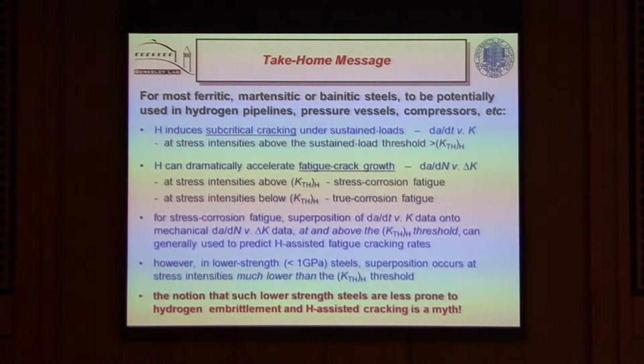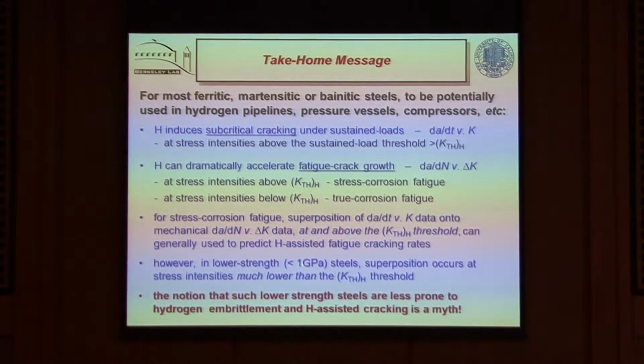And one other thing I might mention here is that some of the ways that this has been done tend to suggest that high-strength steels can be very, very susceptible, and low-strength steels can be far less susceptible to the embrittlement of hydrogen. And I think that is a myth. I think if you look back, you'll see many, many examples where people have used lower-strength steels, and I'm talking about steels less than a gigapascal in strength, thinking that they are relatively immune to hydrogen embrittlement. And in fact, that is not the case. And it's come about because of a lack of understanding of how the experiments are done.